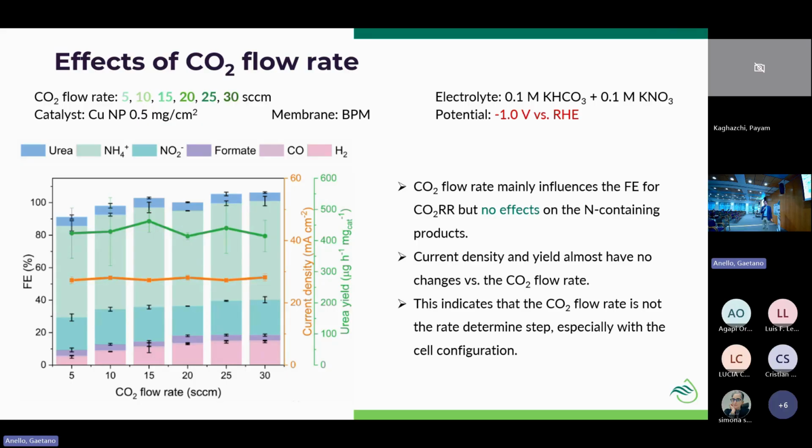Okay. If I remember correctly, we are basically under the assumption that urea decomposition can be a factor, but it's not so fast that it would directly alter our conclusion. If you look at the Faraday efficiencies, they almost reach 100%, so we're not missing too much product. Over the longer term, it does have an effect. If you take a sample and leave it standing for 24 hours and then measure urea, I would imagine that you lost a bit of urea.